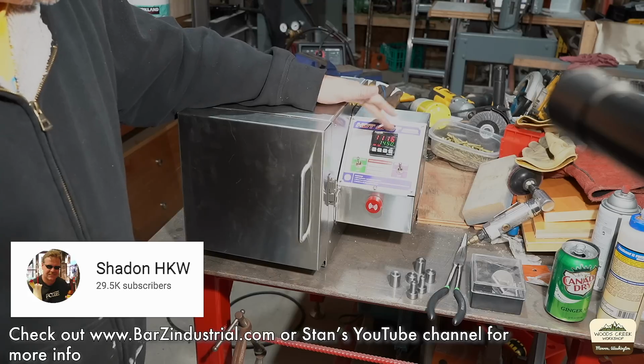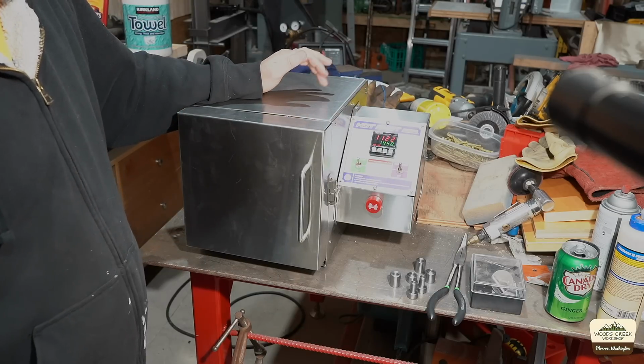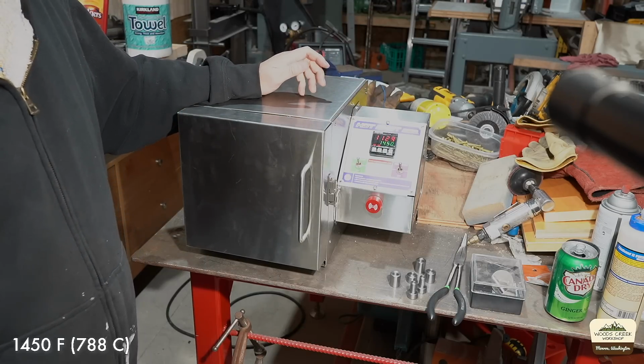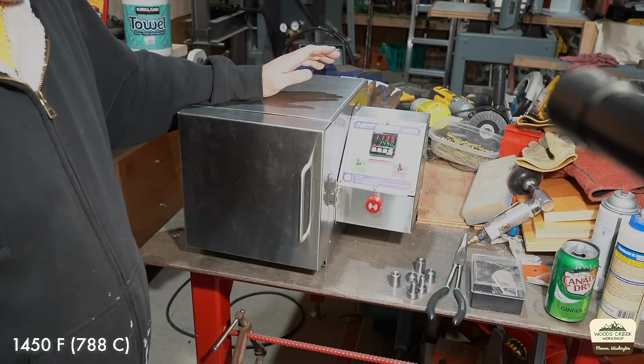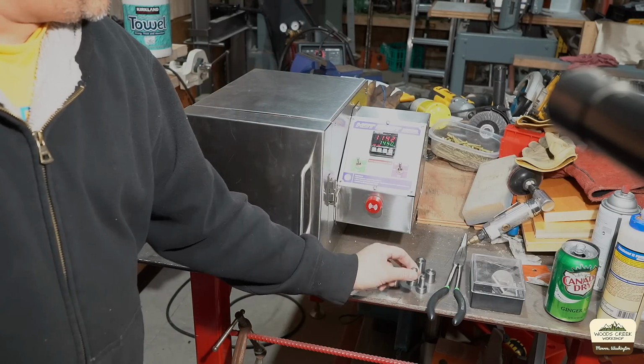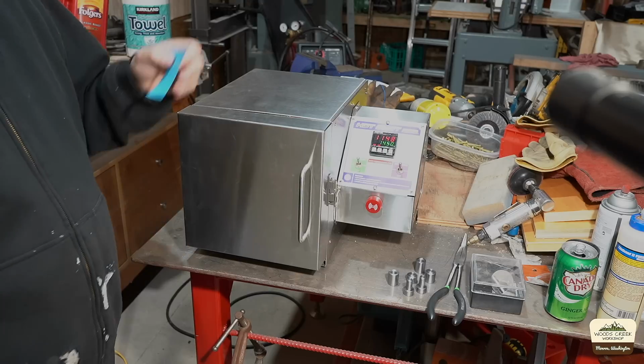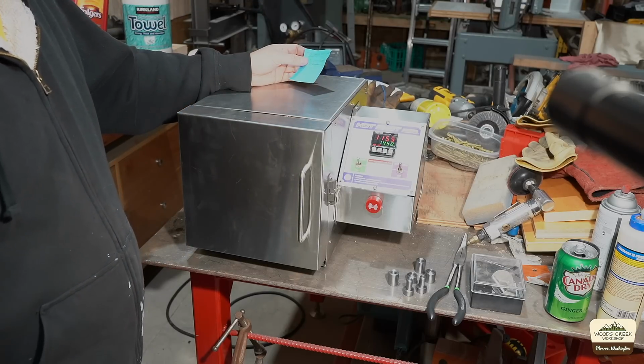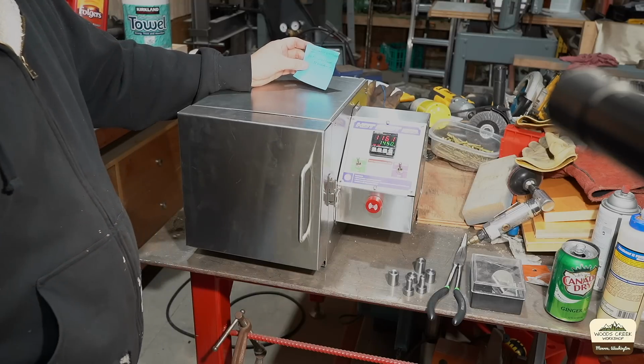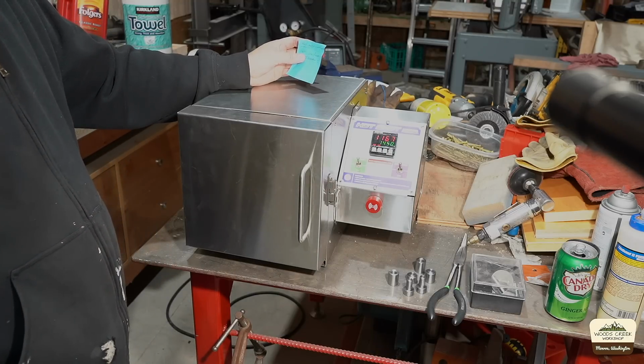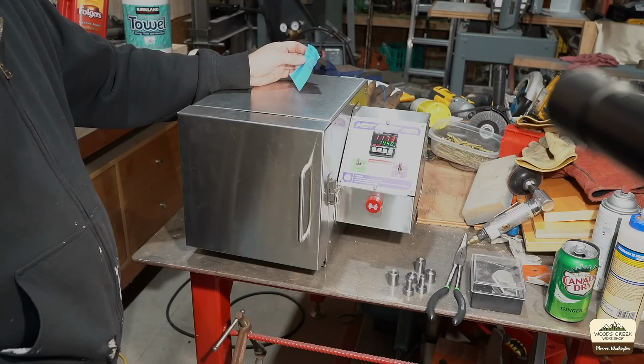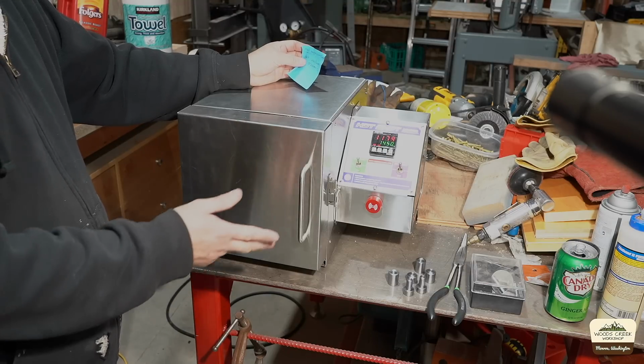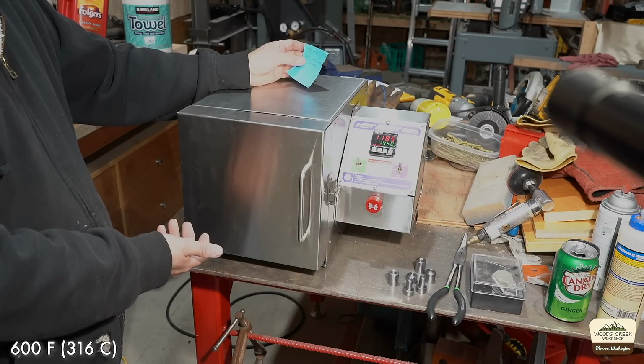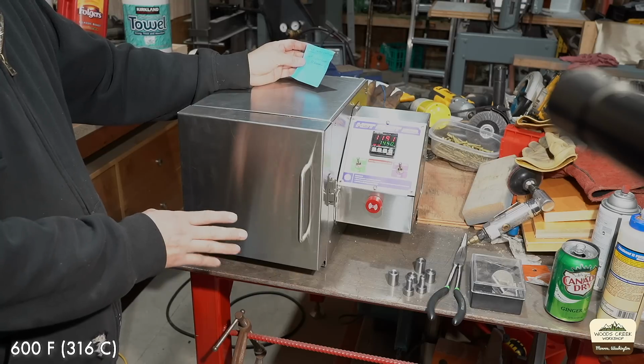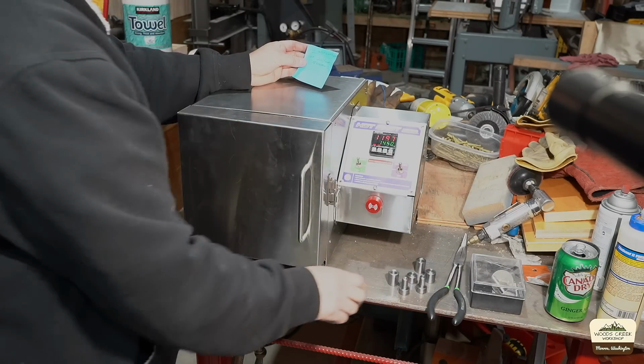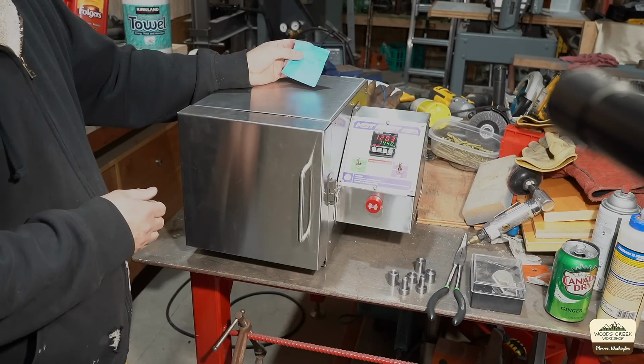Pretty cool. Right now I got this program to ramp up to 1450 degrees Fahrenheit, and we'll soak it for 30 minutes. That's 30 minutes per inch, and close enough. And then we'll quench it into water, obviously, and then later we'll temper it by soaking it at 600 degrees Fahrenheit for 2 hours. That'll bring this down to about 55 Rockwell C hardness.